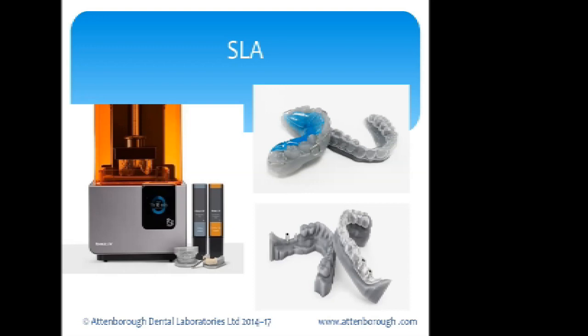If you're 3D printing surgical guides, for example, that material wouldn't necessarily be suitable for intraoral use, or qualified CE marked, because you couldn't guarantee that the material was fully cured, that all of the photo initiator was used up, that there was no free unpolymerized monomer within the build. So I think there's going to be a lot to play out in this story about validated workflows.